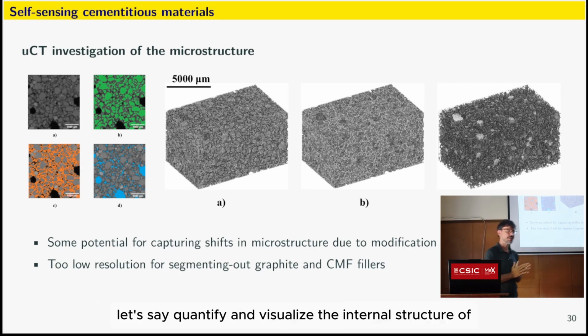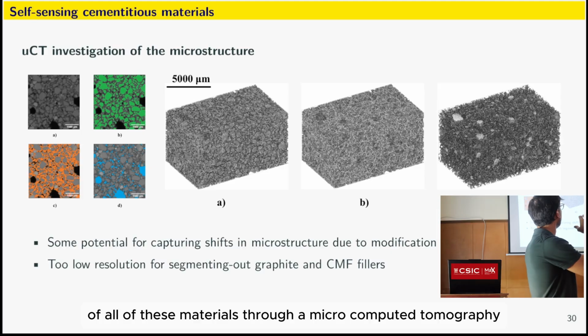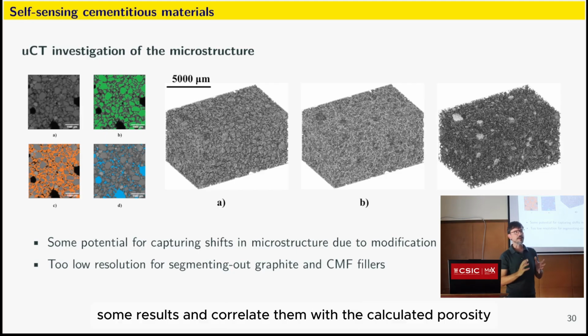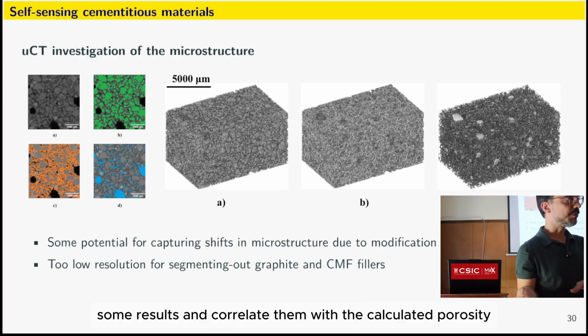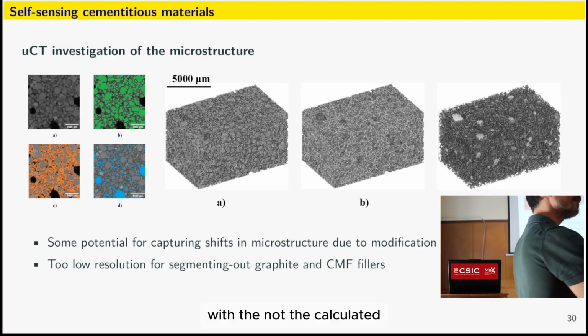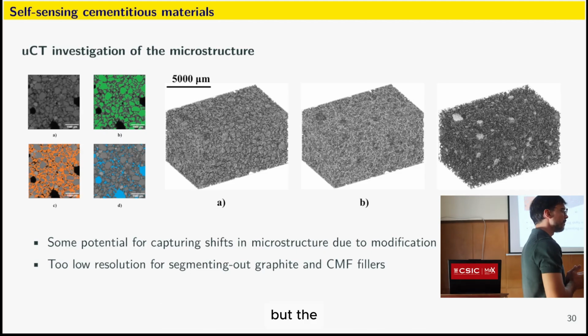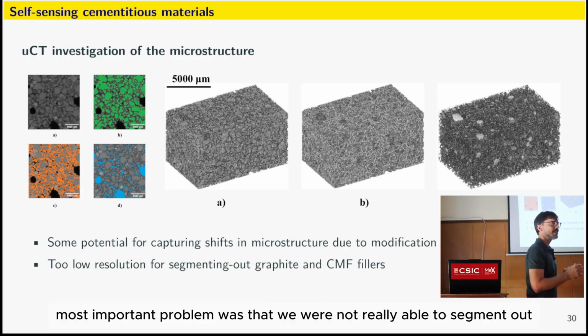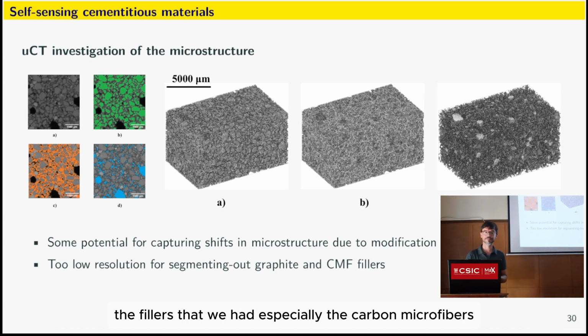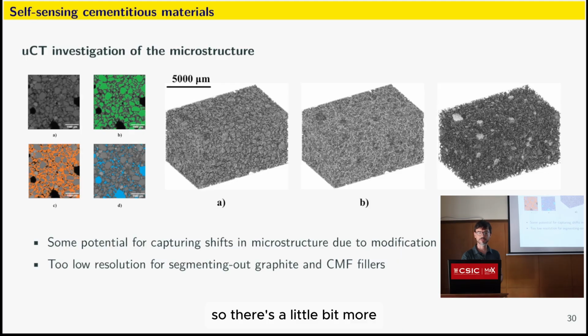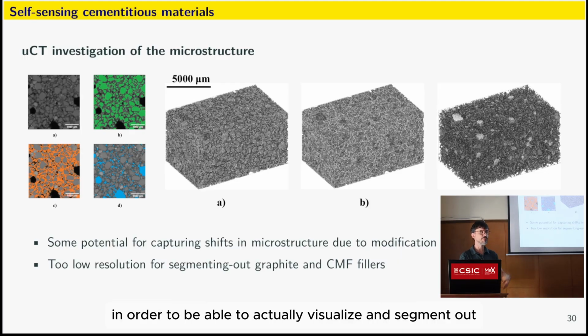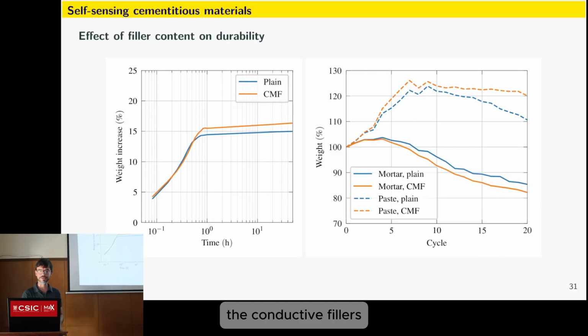We also tried to quantify and visualize the internal structure of all of these materials through microcomputed tomography. We managed to get some results and correlate them with the experimentally determined porosity. But the most important problem was that we were not really able to segment out the fillers that we had, especially the carbon microfibers. So there's a little bit more work to be done in that regard in order to be able to actually visualize and segment out the conductive fillers.